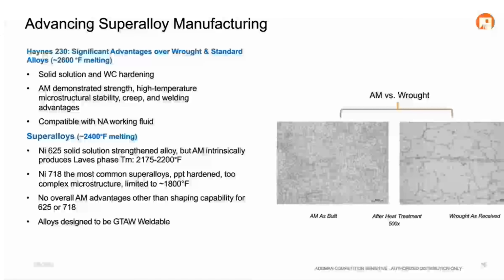What you're seeing here is a comparison between the right and the left, the right being the wrought and the left being the additive manufactured material. We're able to get these tungsten carbides forming coherently within grains at very fine length scales, but also along the grain boundaries. We have really refined grain boundaries, as is typical of a rapid solidification process. How that manifests in material properties, I'll show you on the next slide.